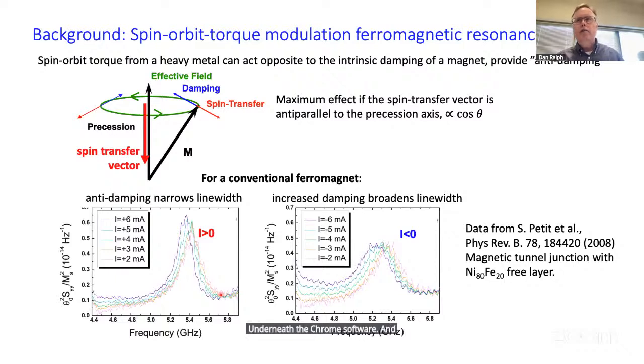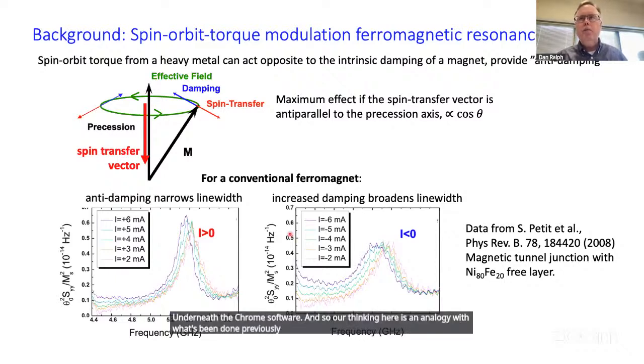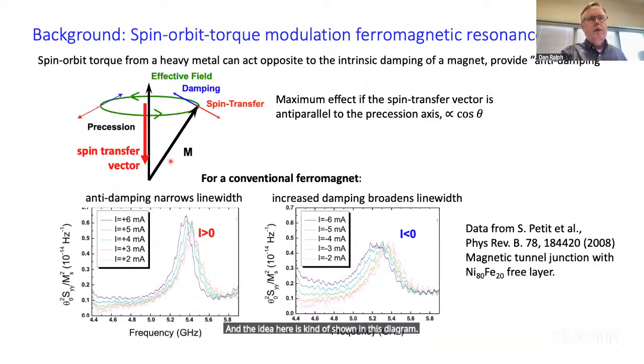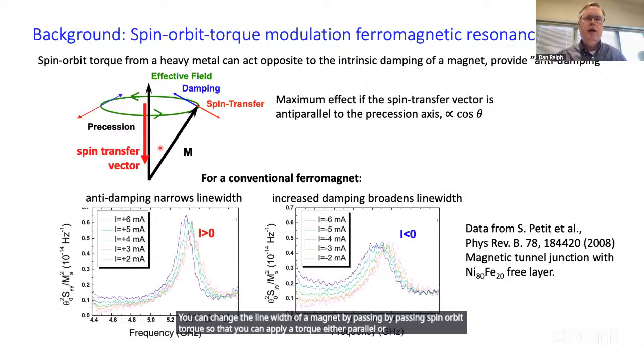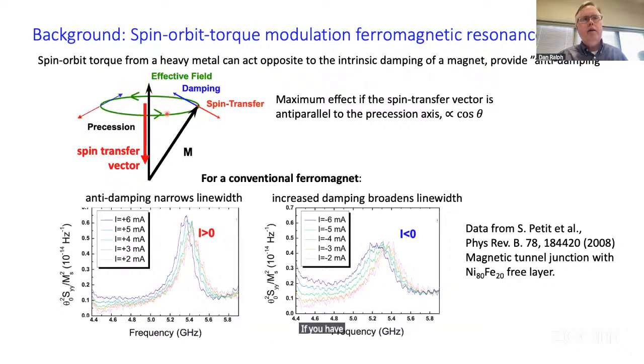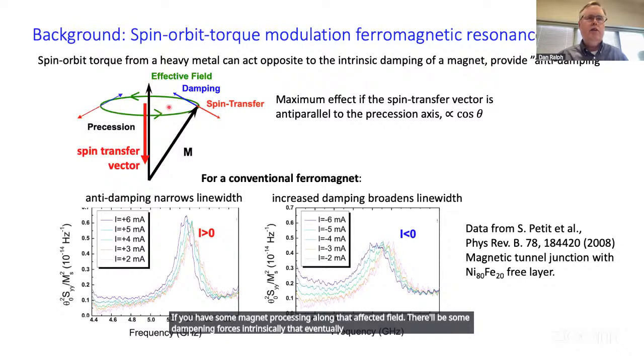And so our thinking here is an analogy with what's been done previously using spin torque modulation of ferromagnetic resonance within ferromagnetic thin films. And the idea here is kind of shown in this diagram. You can change the line width of a magnet by passing a spin orbit torque so that you can apply a torque either parallel or perpendicular to the precession axis of a magnet. So in this diagram, you can think about if the effective field is vertical here, if you have some magnet precessing along that effective field, there'll be some damping forces intrinsically that eventually cause that precessional motion to spiral and come to rest along the effective field.